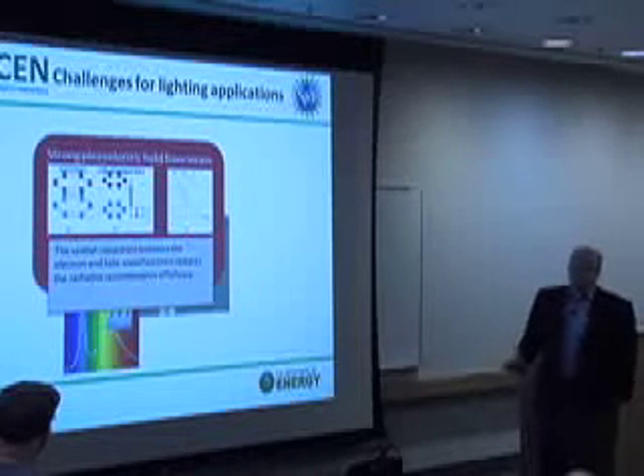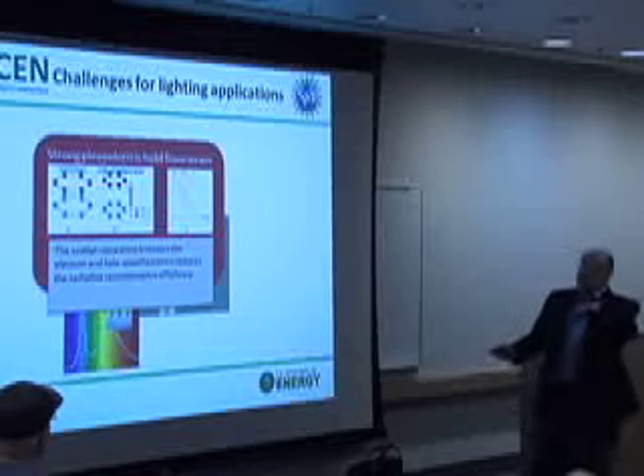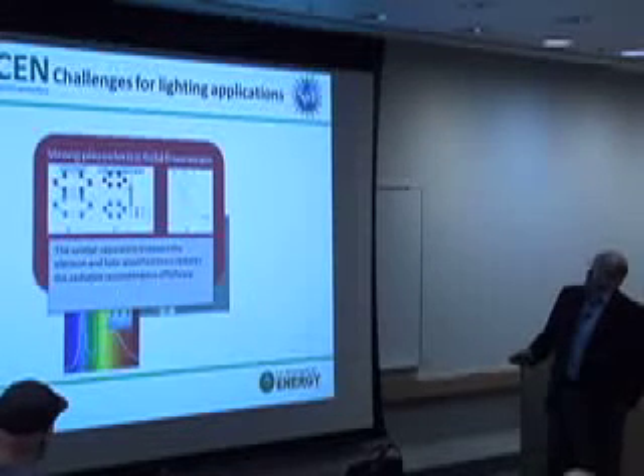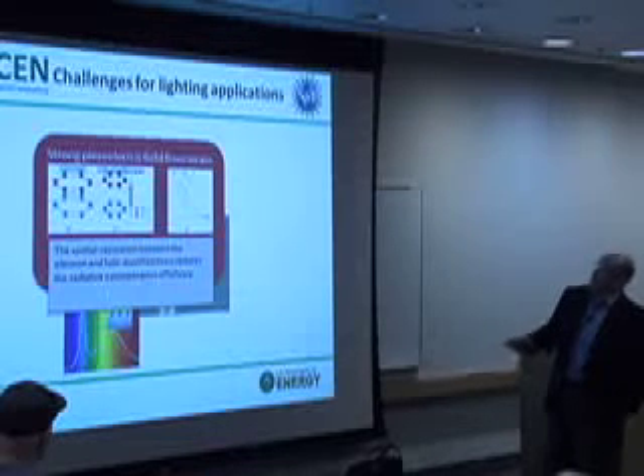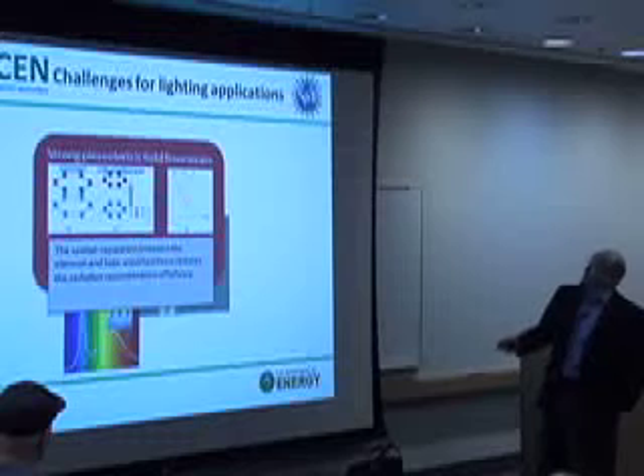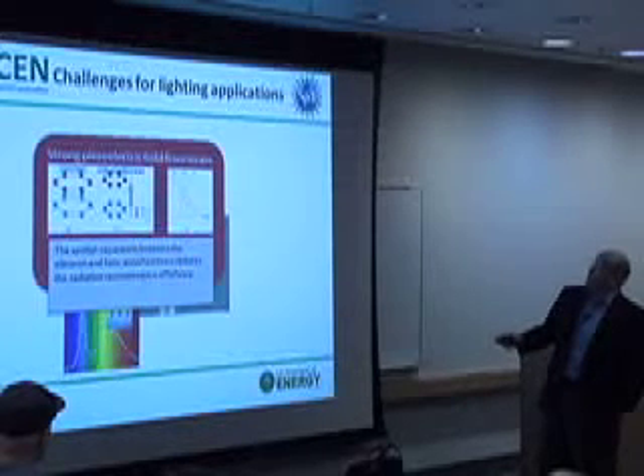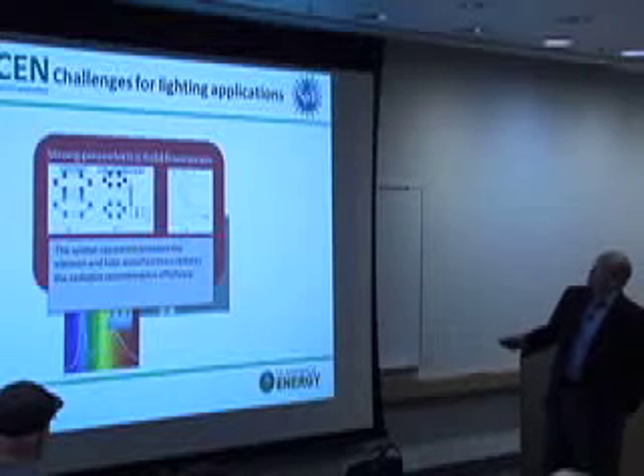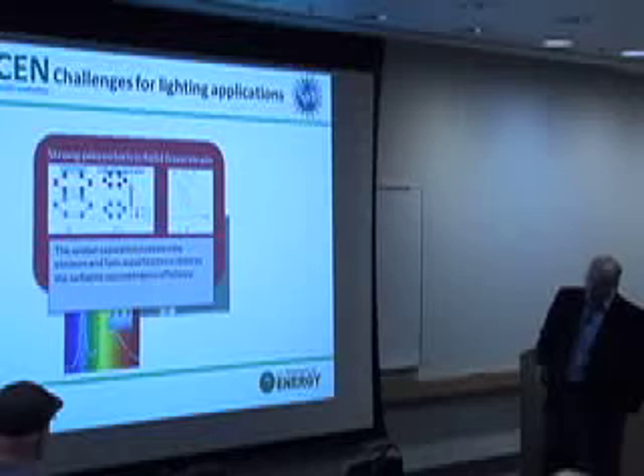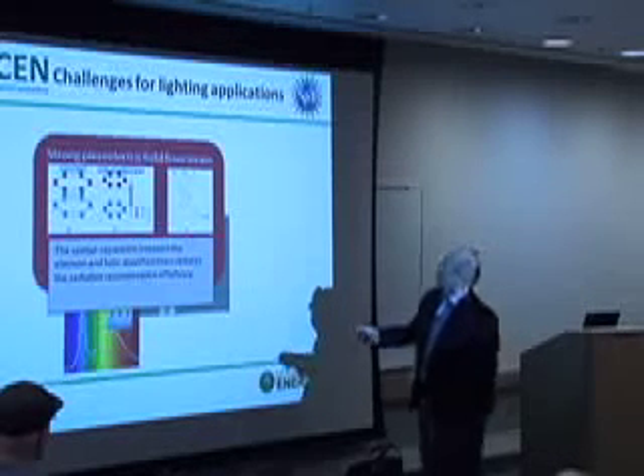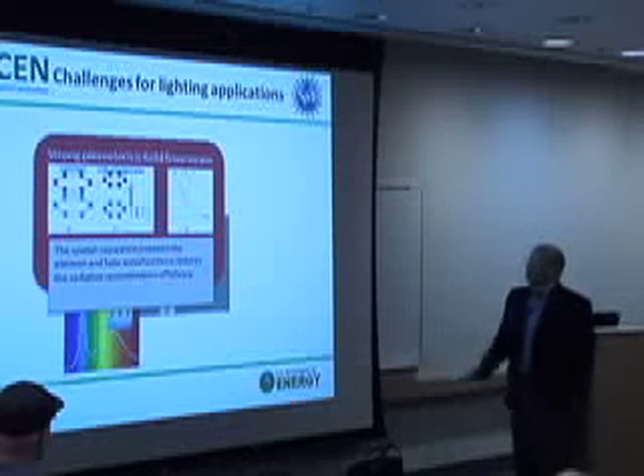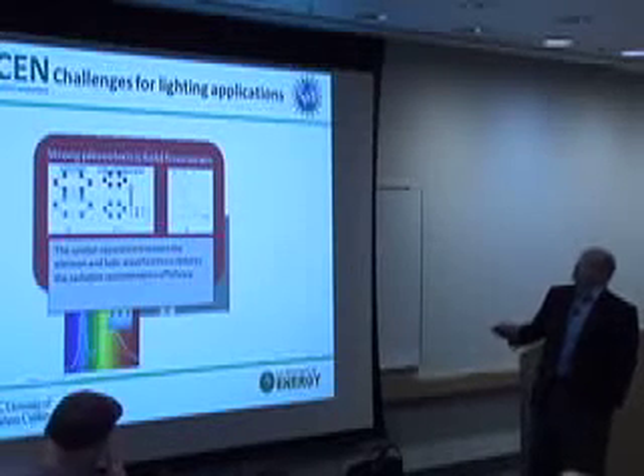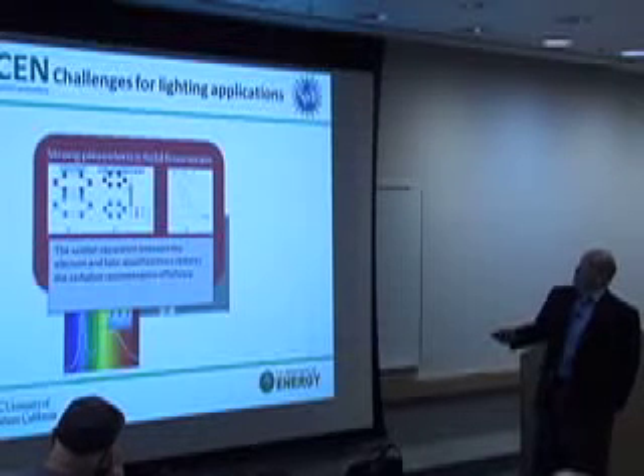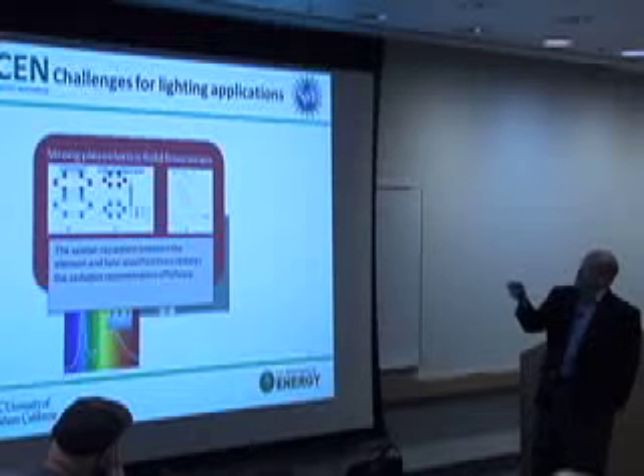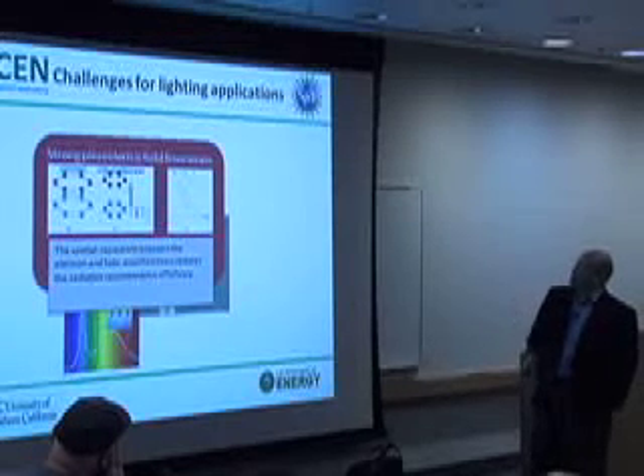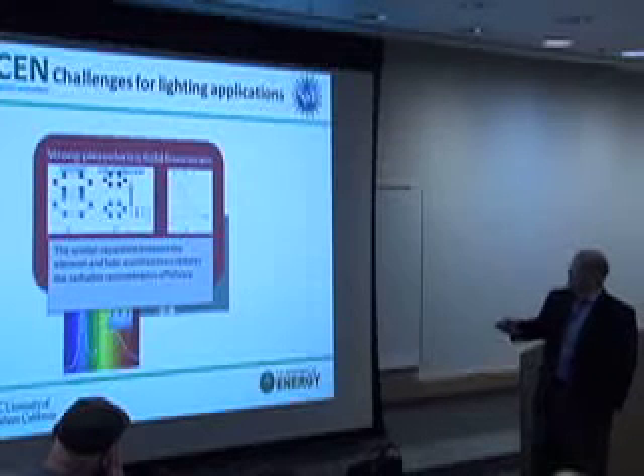Presently, for the vast majority of the products, they're grown on the C plane, which, because of the particular ionicity of the bonds in the structure, leads to a piezoelectric effect that creates an electric field in the vicinity of the quantum well that displaces the electron and hole wave functions unless you make these wells really thin. So empirically, even before all of these effects were understood, I believe, people made these quantum wells only 2 to 3 nanometers thick. And there are some downsides to that.